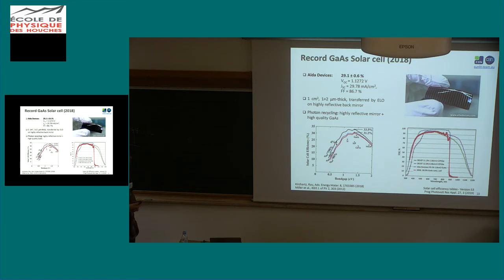And you can also have photon recycling, meaning, as mentioned by Uwe, that if you have a radiative recombination, you will have a re-emission of photons in all directions, and some of these re-emitted photons might be light trapped inside the gallium arsenide and reabsorbed once again. And this is not lossless anymore, because it contributes to increasing a little bit the density of photogenerated carriers, and we saw that the quasi-Fermi level splitting is linked to the density of photogenerated carriers. So you will increase by this means the VOC, or the open circuit voltage, of your cell.